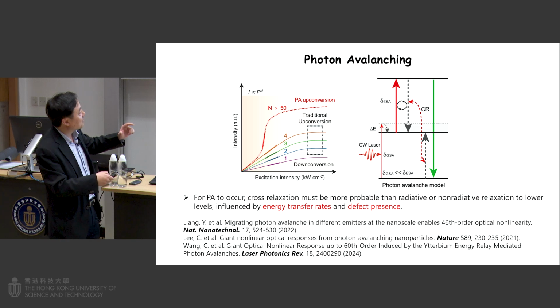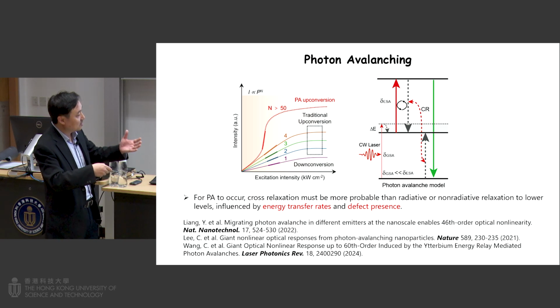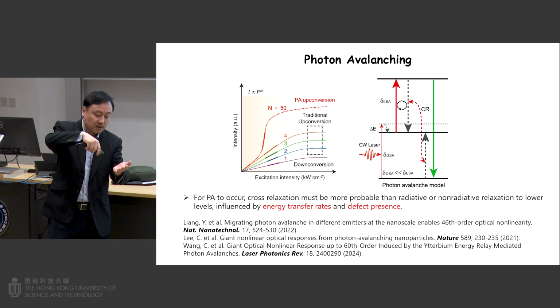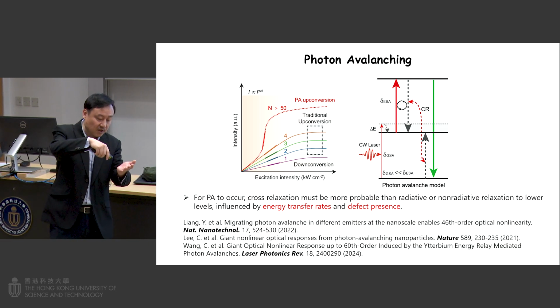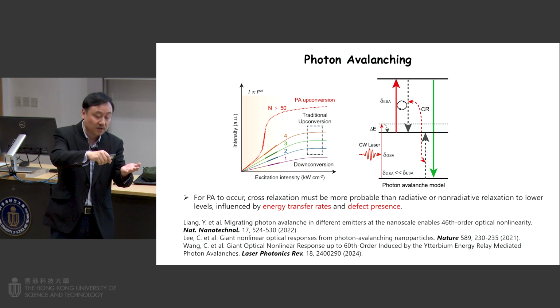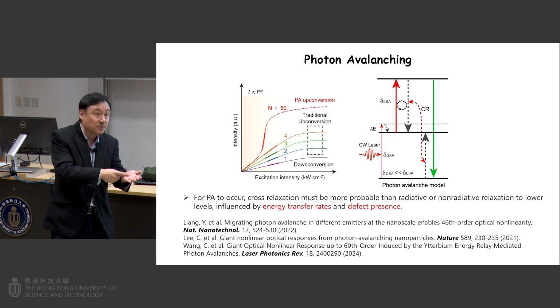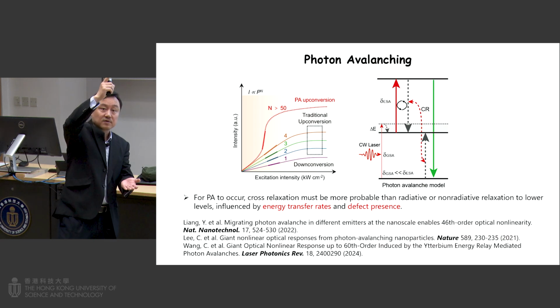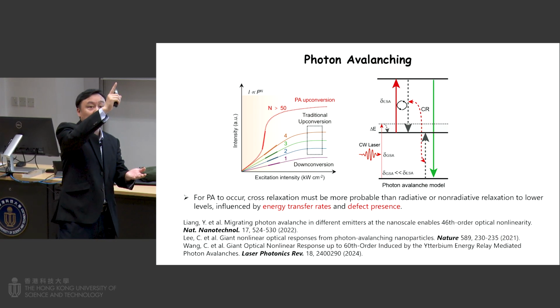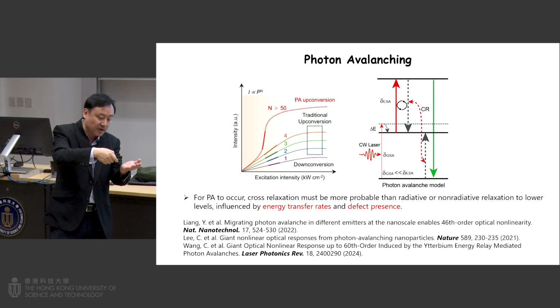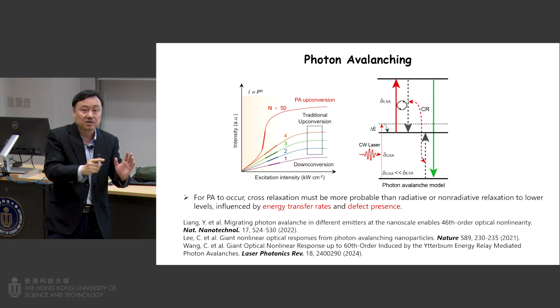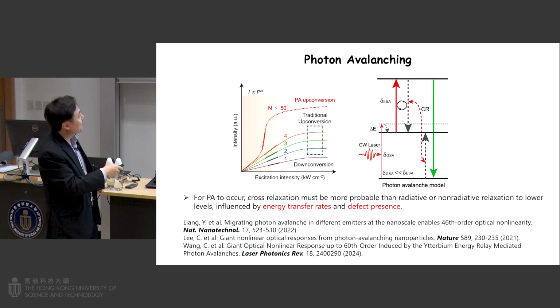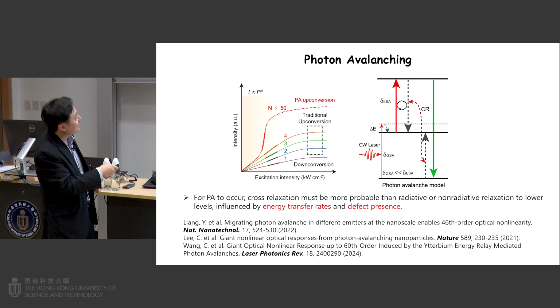Okay, why is that? Because you can achieve high nonlinearity. You can see the slope here, very sharp. So it means you excite these materials, okay? Initially, at a low excitation intensity, the materials show no luminescence. You increase a little bit, then suddenly the luminescence goes up significantly. Then if you further increase intensity, it goes down. So this is very interesting. Look at the slope here. So one photon, two photon, you actually increase. So this is the excitation intensity.